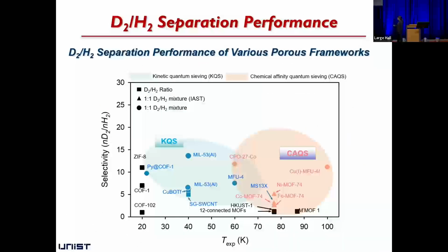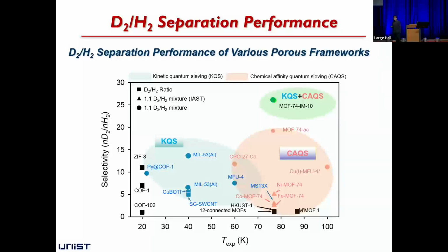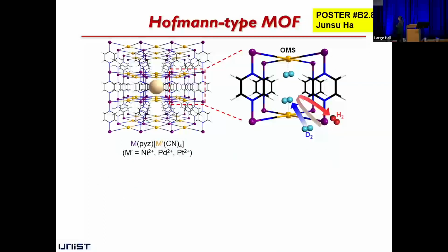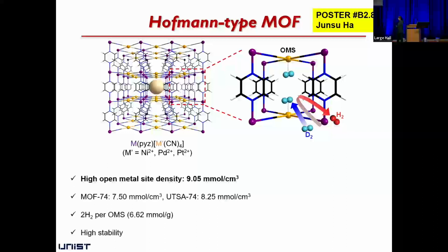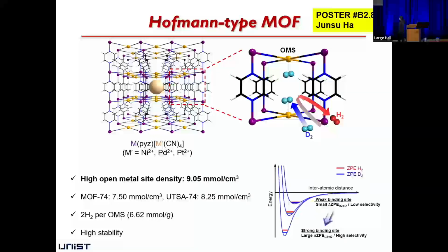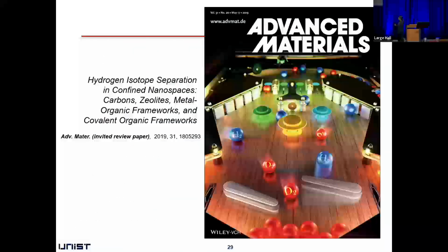So if you see here, just by putting this KQS and CAQS in one system, we could see the synergistic effect, and we can have very high selectivity with the metal organic framework. To see the chemical affinity quantum sieving effect, we also tested a Hofmann type metal organic framework. Hofmann type metal organic framework has the highest open metal site density. This is much higher than MOF-74. So if you are interested in this topic, also please visit my student tonight, okay? And I think there is still a long way to go to find the ideal and optimum MOF system for hydrogen isotope separation.